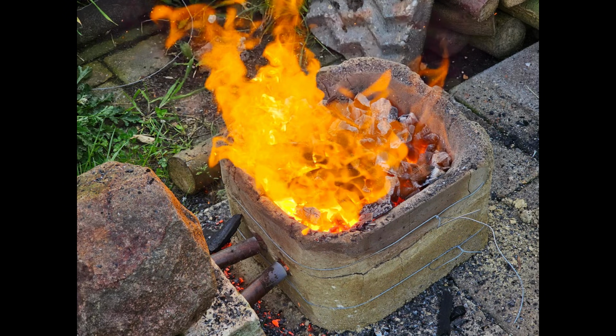Some of the Ulfberht swords, particularly with the +T category, have been analyzed to have a slag content with 16% calcium in its slag, and furthermore have a 2 to 1 calcium to potassium ratio. It is therefore also found in the actual Ulfberht swords that the mass balance for calcium, potassium, but also for manganese fits with hearth refinement, by looking at the slag composition inside of the steel of actual Ulfberht swords.